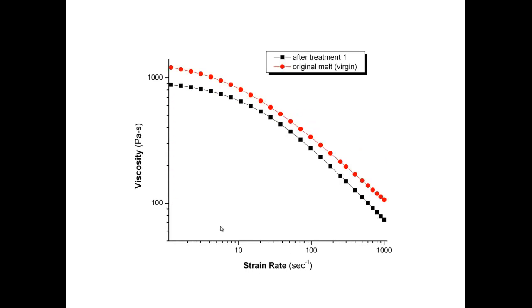Here, same, but I am showing a little difference in that the Newtonian viscosity is different. As you can see, the black curve, which is after the treatment, has a lower Newtonian viscosity, and the pseudoplasticity is increased. If you compare it to the original, the MFI value would be higher, and the pseudoplasticity is also improved after treatment. But as I said, you go back to 275 for 5 minutes, and of course after also having all this heating of the pellet to make discs in a compression mold, and then another heating in the rheometer itself to reach the temperature of 225, all this at the end, you're recovering and recovering and recovering. This is what's left.